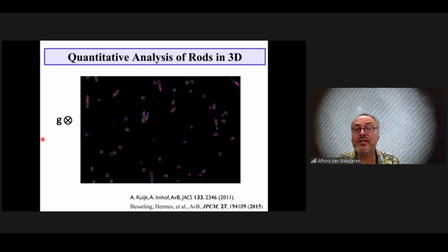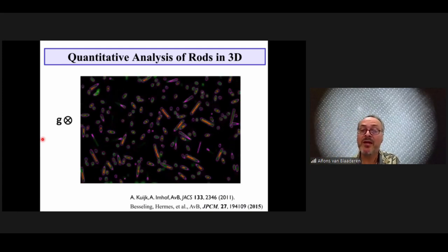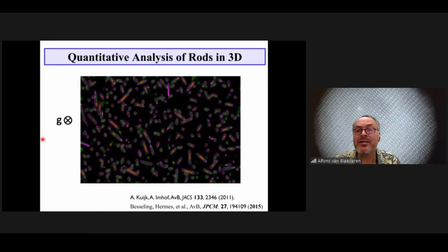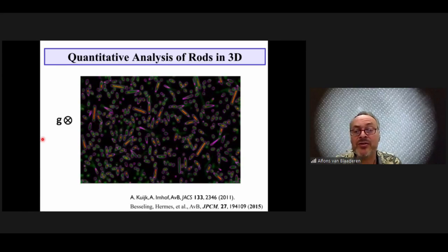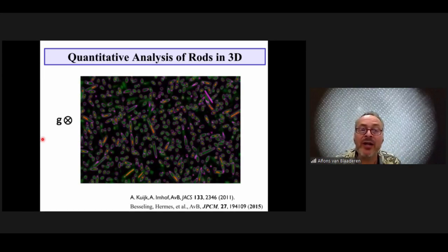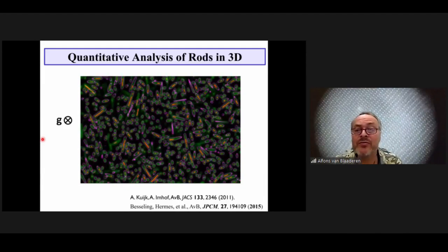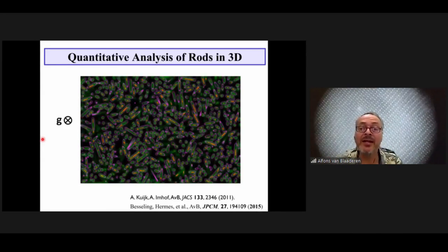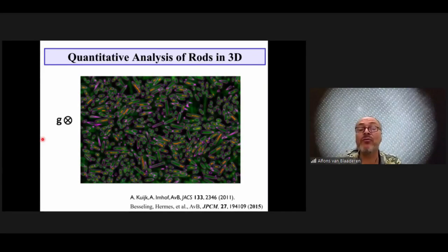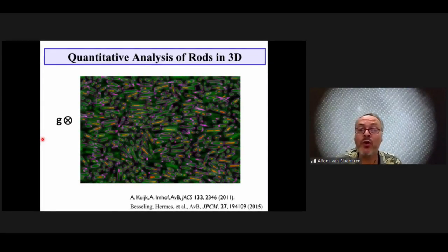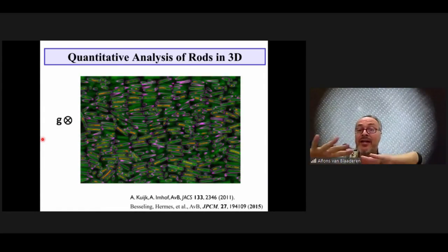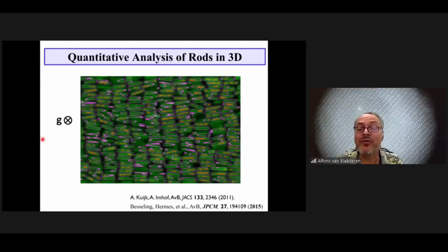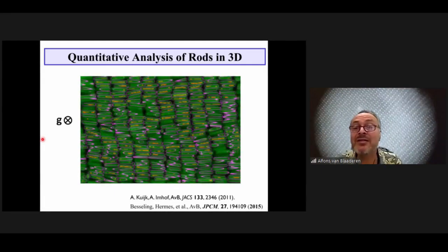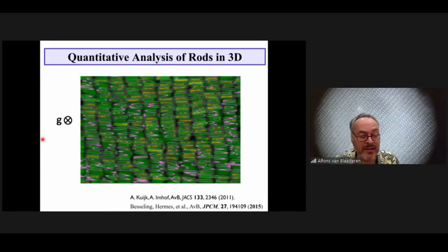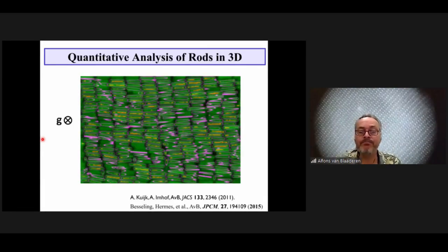We can now go through a 3D data set, and this is a 3D sample that has been equilibrated in the gravitational field. So we see these rods going from the top to the bottom, being many particle layers stressed by the osmotic pressure. We first see a colloidal liquid of these rods, and all the purple is the 3D analysis of all these rods in the 3D data set, so we can find all their orientations. And then at some point you get a first order phase transition, and you get a liquid crystal, a smectic liquid crystal formed by these rod-like particles.